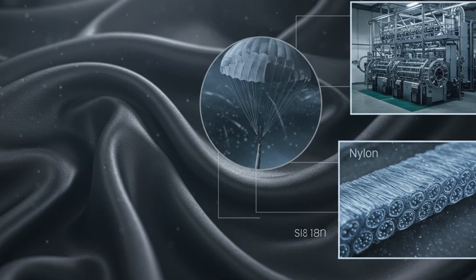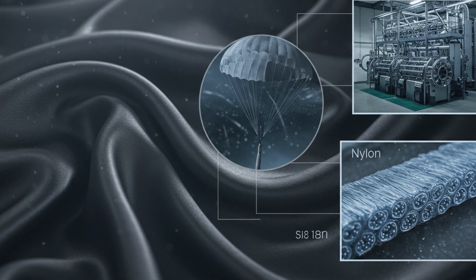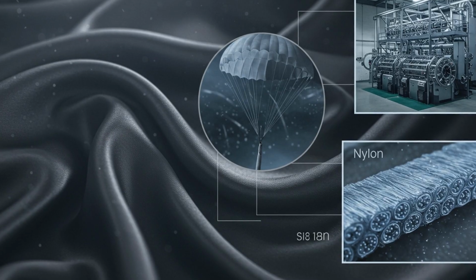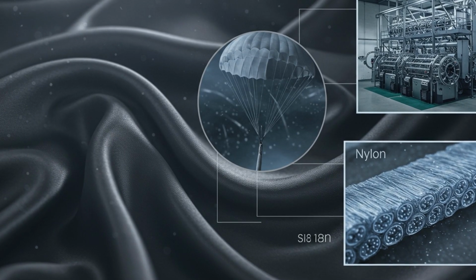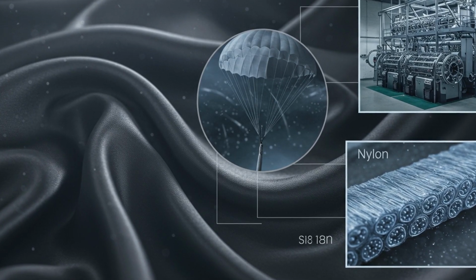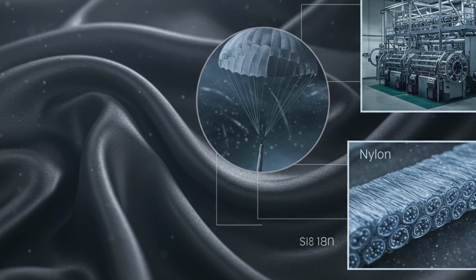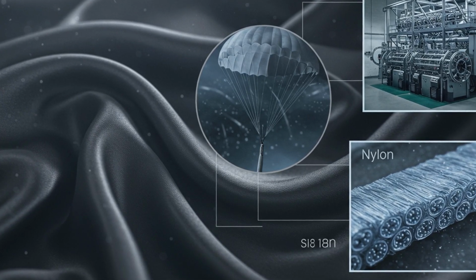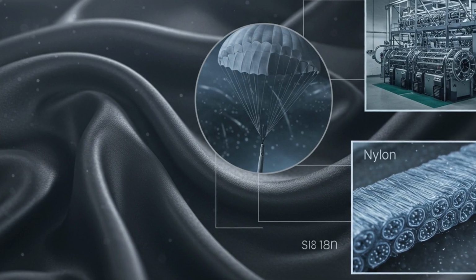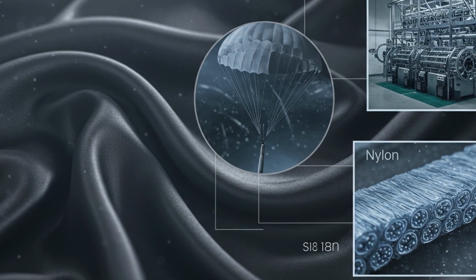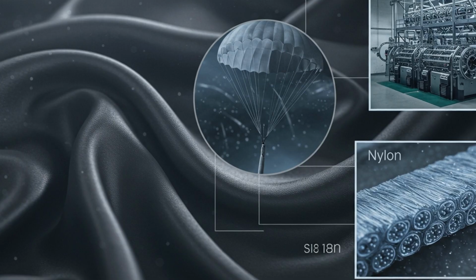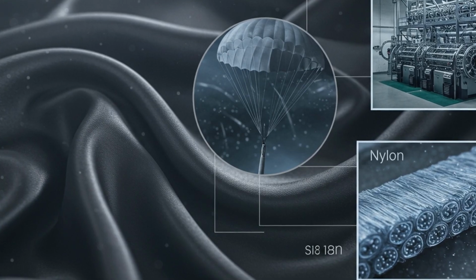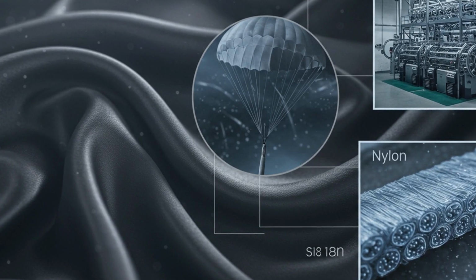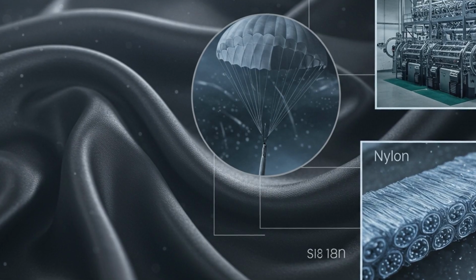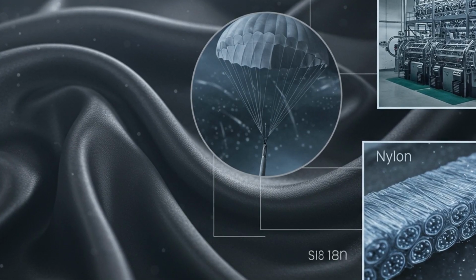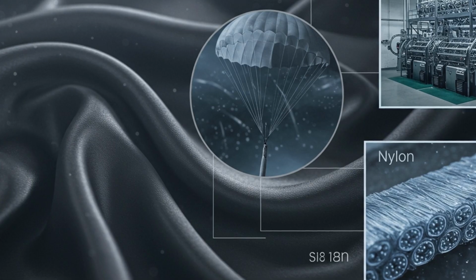What began as a laboratory polymer is now in parachutes, airbags, carpets, toothbrush bristles, and, famously, stockings that replaced silk. Engineers tuned molecular weight, draw ratios, and finishing chemistry to hit targets: strength, elasticity, sheen, and hand. Compared to silk, nylon offers consistent properties, lower cost, and mass manufacturability. Nylon 6,6 melts around 265 degrees Celsius, and Nylon 6 melts around 215 degrees Celsius, giving processors different windows for melt processing. Its semi-crystalline structure provides toughness and abrasion resistance, while chemical affinity for acid dyes creates bright, durable color.